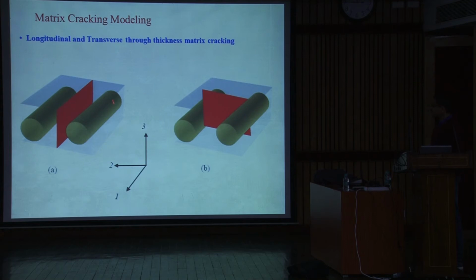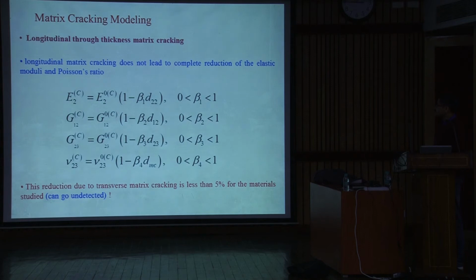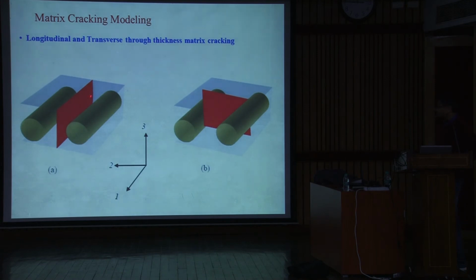So when you are having the crack, and if I am looking at this volume and at the stiffness that I have, what you get is that there is not a complete reduction in the stiffness. You will still have some stiffness. That is why we have put these parameters. These parameters are, again, between 0 and 1. So there are two types of cracks, as we said here: a longitudinal crack and the transverse crack.